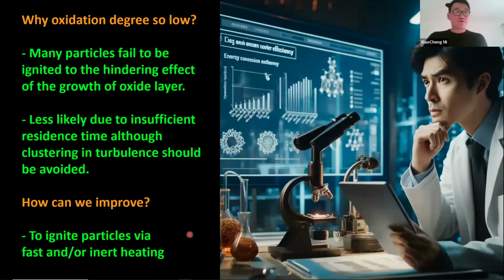Okay, so we come back to the questions that we asked before. First of all, why is the oxidation degree so low? What we see from our lab scale burner and also the material characterization shows that many particles fail to be ignited. Theoretically, we showed this failure of ignition is due to the hindering effect of the growth of the oxide layer. And actually, it's very unlikely that this low oxidation degree is due to an insufficient residence time, because for iron particles after ignition, the combustion time is very short.